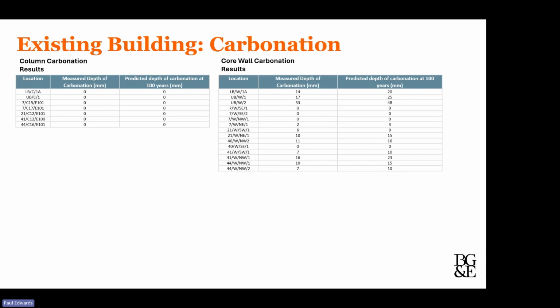Slightly different in the core walls on the table to the right, where the majority of the carbonation, predicted carbonation, were after 100 years, bearing in mind it's 100 years because effectively 50 years in terms of the existing building and want to justify it for another 50 years.